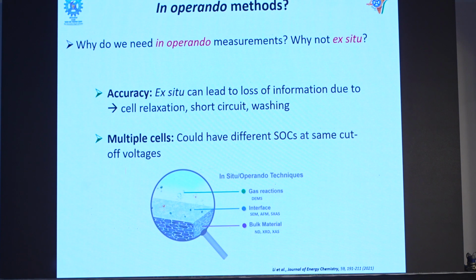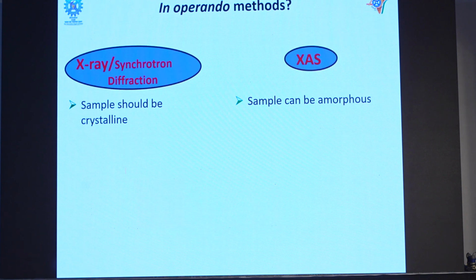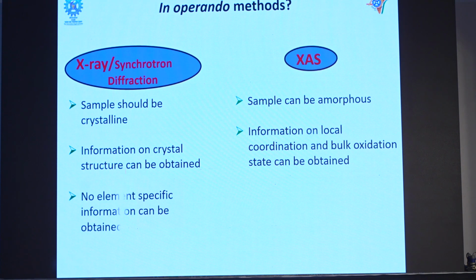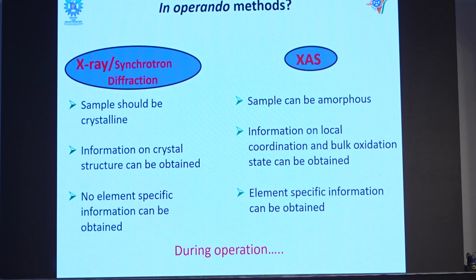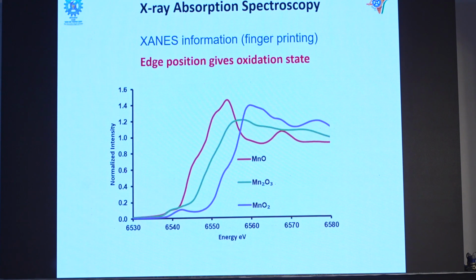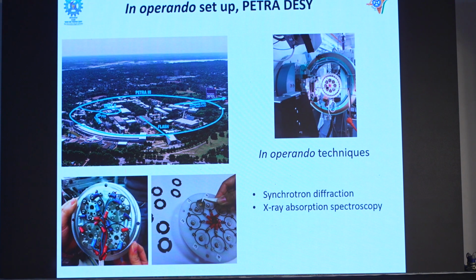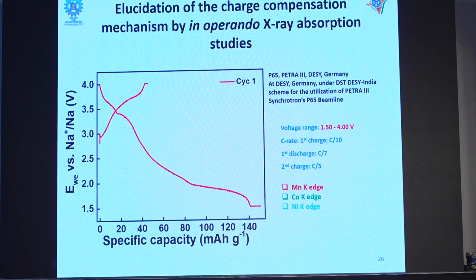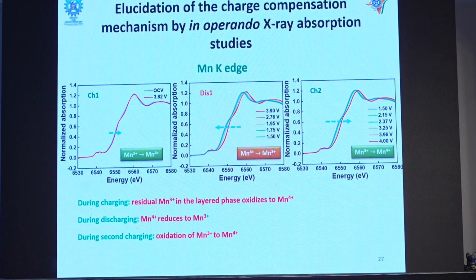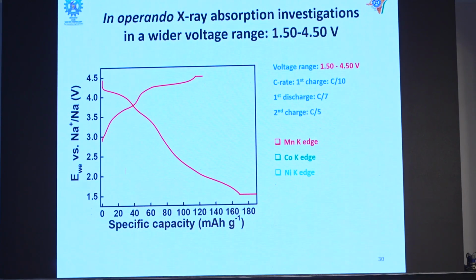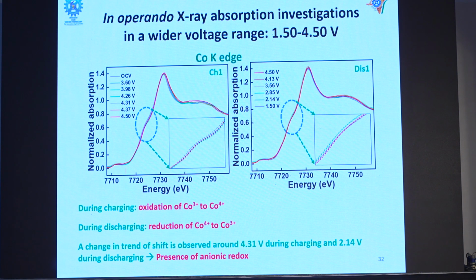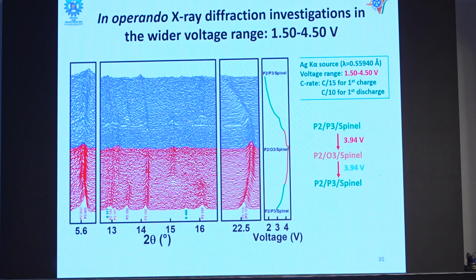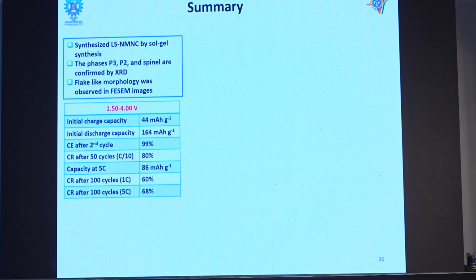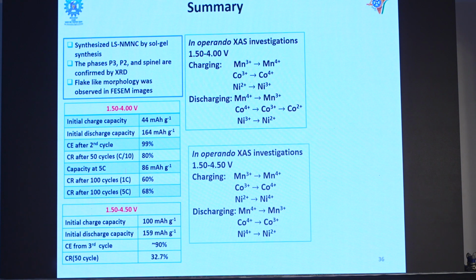So in summary, I have only one summary slide left. When we have the cutoff voltage of 4, the electrochemical cycling is very good, and we have a high rate capability. And when we increase the upper cutoff voltage to 4.5, the electrochemical reactions are getting more in number, but we end up in a loss of capacity and less rate capability. And we can see that when the upper cutoff voltage is restricted to 4 volt, we can tune the cobalt 2 plus reaction in the system.